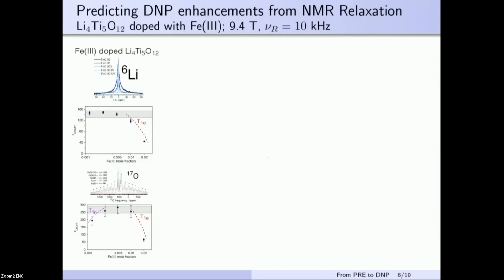And of course, this condition fails at some point. It fails in the low concentration regime, because at this point the intrinsic relaxation mechanism of the nucleus starts kicking in. I forgot to mention that the condition for this distance independence is that the dominating relaxation mechanism is the PRE, the paramagnetic relaxation enhancement. And in the high concentration regime, we also start deviating from this behavior at some point. This is because the electron-electron coupling starts becoming stronger, and as I showed you before, the electron relaxation time starts dropping.